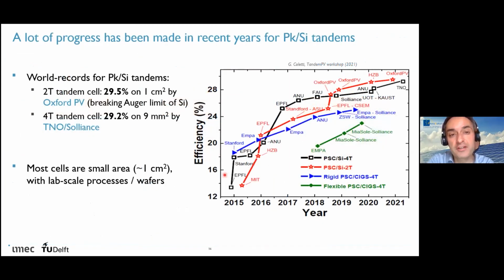For perovskite on silicon tandems, in the last years a lot of people have started investigating this, including companies. At the moment, the world record efficiencies achieved for perovskite on silicon are 29.5% for the 2-terminal device, done by the company Oxford PV, and 29.2% by TNO in the Netherlands, for a 4-terminal device. In both cases, this efficiency is already above the theoretical limit of crystalline silicon.